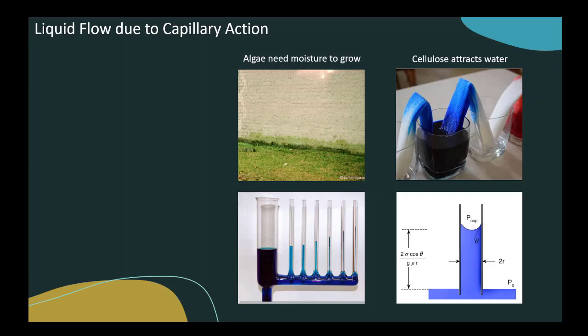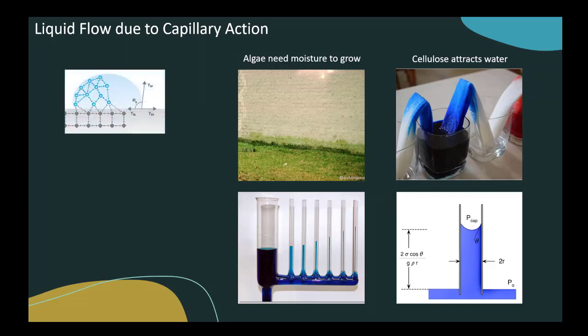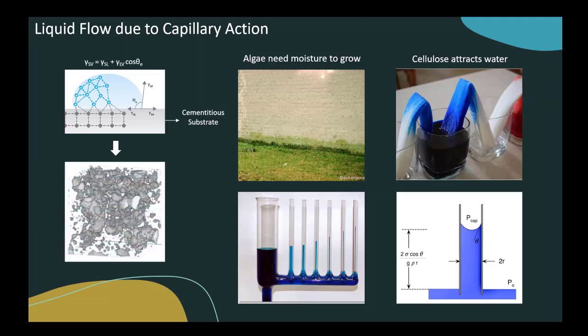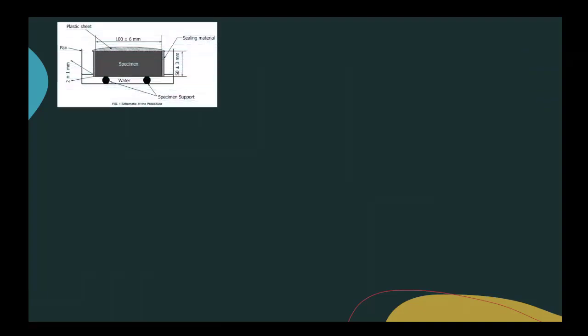So that was my initial thought during my PhD. What if I place a single water droplet on the surface of cement paste and see if I can indirectly measure porosity in the cement paste? That was my initial thought. So this is the geometry of liquid absorption in the ASTM test.